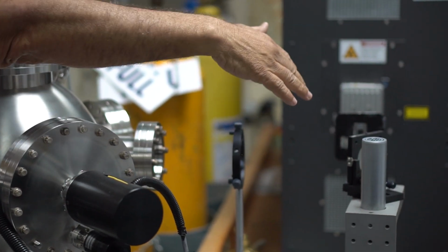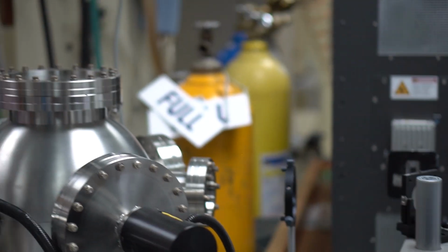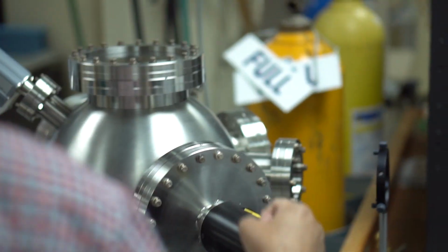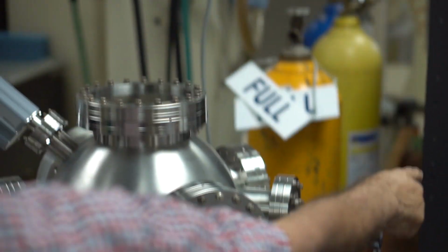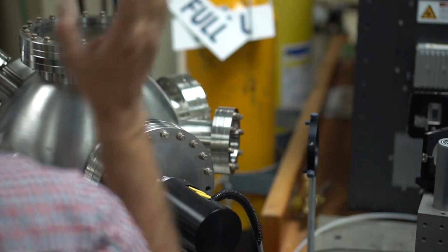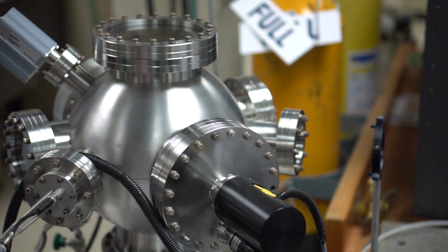We have this turning mirror which turns the beam 90 degrees. So the beam is coming from there. You can see all our optics here is big. Their optics was very small because their laser beam was just 6 millimeter. Here the laser beam is almost 2 inch by 1 inch. So we need big 2-inch optics here. That's why this turning mirror is so big, and the lens is so big. We even made the aperture ourselves to make the beam very clean.